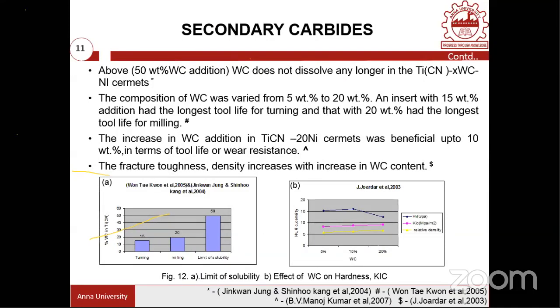And what is the percentage of addition that is recommended for every case? The tungsten carbide, you can add up to 50%, because it has solubility up to 50% in TiCN based CERMET. But above 20% of addition, there isn't any good improvement in the mechanical properties like hardness and toughness. Okay, therefore you can go up to a maximum of 15 or 20%, where you have a remarkable improvement in the hardness and toughness value.